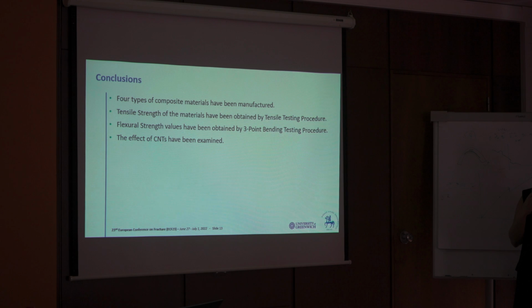So actually this is just to sum up what we've done. And for this study, as I mentioned, this is a quite preliminary study. After running some more experiments for the material properties testing, we are going to manufacture more specimens, and then we are going to investigate the fracture toughness values of these materials, because as I said before, the epoxy was designed in order to minimize the delamination within the composite materials.